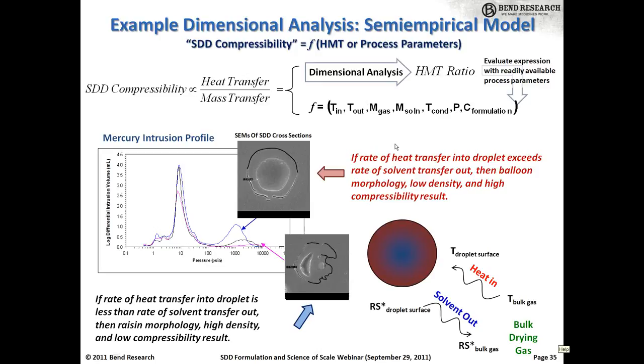For high HMT ratios, the numerator is larger than the denominator, so the heat transfer rate into the droplet is faster than the solvent transfer rate out, and you end up with the hollow sphere morphology SDD. And the converse is true for the low HMT ratio. That's more like the raisin-like particles.